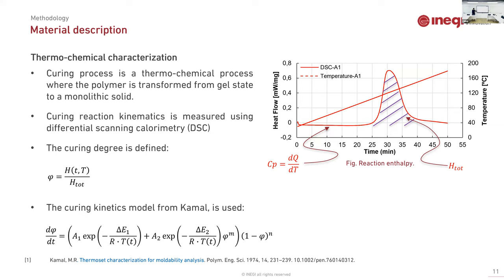How can we, after that, model the curing process? For many years there have been a lot of models to analyze the curing process. One of the models that is very used and very simple is the model proposed by Kamal. This is the equation. You basically have some fitting parameters, which are the activation energy and some coefficients, to fit the cure. With this, I can model the curing kinetics in the resin or even in the composite.